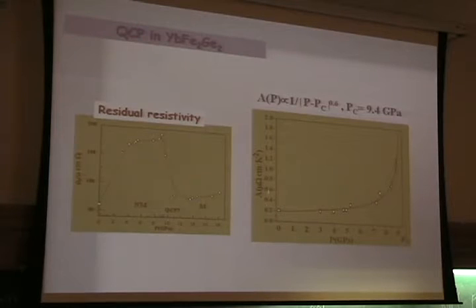Also, we have the A coefficient for this system, and you see how it diverges near the PC. Also here we have the residual resistivity, and you see a big drop near this quantum critical point. That may be because of the ordering of the moments in this region, and then you decrease the scattering of the quasi-particles, and then you see this big drop here.